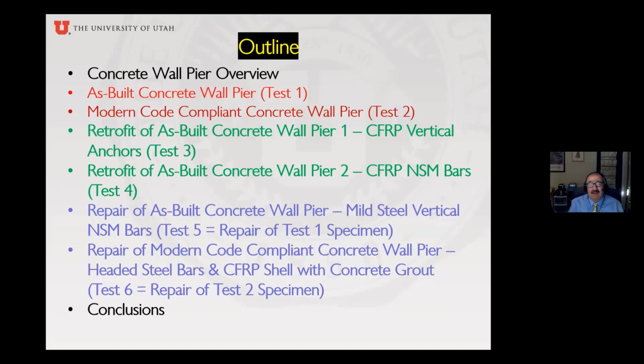I have here an as-built concrete wall pier, which means this was a concrete wall pier that was built with the standards before any seismic requirements. I have a modern code compliant concrete wall pier, which is a wall pier that actually meets the current seismic requirements. Then we built a couple more specimens identical to the first one, the as-built, but we retrofitted it. The first retrofit was vertical carbon fiber anchors, and the second retrofit was carbon fiber near surface mounted bars. So you would think that we built 4 specimens and that would be the end of it.